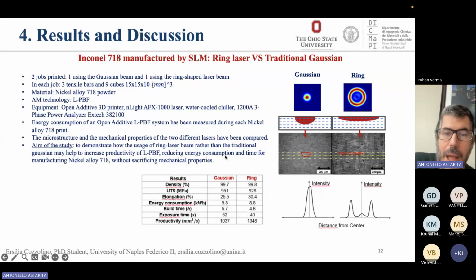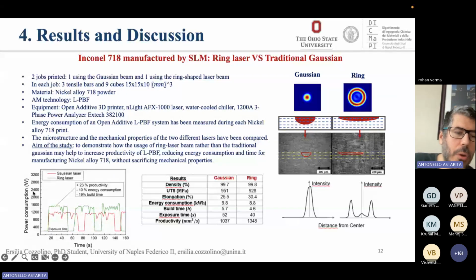Okay. Again, we performed a full experimental campaign and we measured the power consumption over time. You can see the power consumption over time for both the processes, Gaussian laser and ring laser. By using ring laser, we were able to improve the productivity and to reduce both energy consumption and build time. As you can see, each time that you reduce the build time, you increase the productivity and you decrease the energy consumption. Why? Because if you remember the previous formula, the formula for specific energy consumption in additive manufacturing, you can see that by reducing the time, the process time, you reduce the energy consumed.